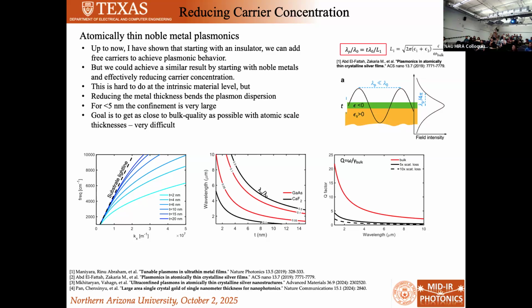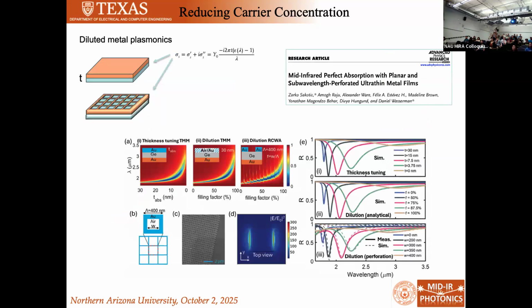And the minute you start being able to get this strong confinement at IR frequencies, your loss goes through the roof, right? So we had been working on these sort of perforated metal films because we had been using that paradigm for perfect absorption. We were trying to do it with metal films, and we realized that to get perfect absorption using a metal film, we had to go to thicknesses that we couldn't grow. So we thought, well, what if we just poked holes in our metal, right? And we effectively reduced the permittivity because these holes are so sub-wavelength that light doesn't really see the periodicity. And we can effectively reduce the permittivity and reduce the loss, and we can essentially impedance match these to incident light and get perfect absorption. And so we had a nice paper that, again, led by Zarko, showing that worked.